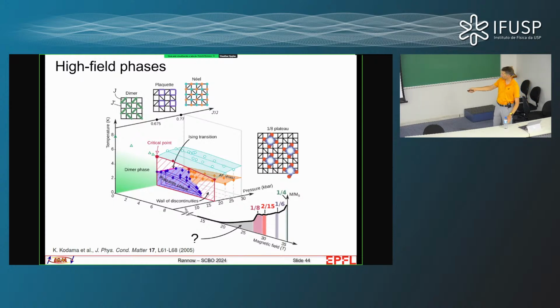Now, that was a phase diagram as a function of temperature and pressure. We can also apply magnetic field to this, and we have to apply a large magnetic field because of the 3 millivolt gap: in order to close the gap with a magnetic field, we have to go all the way up to 20, 30 Tesla. There have been beautiful predictions and even some work using NMR, which I mentioned in the introduction, that up here you can create bound states of excitations which form a 1/8 ordered crystal, like a Wigner crystal of triplets, if you want. But magnetization increases already a little bit before.